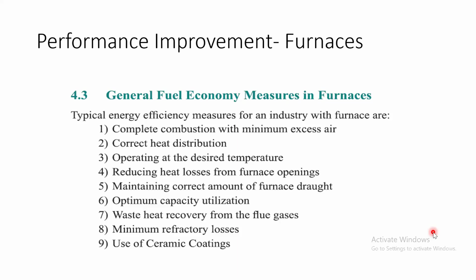And last is use of ceramic coating. Mind well, for insulation purposes and all other purposes, particularly to reduce the losses due to radiation and all. In major cases where the temperature exposed is more than 300 or 400 degrees centigrade, ceramic coating is very important, and it is also important for protection against high temperatures of 500, 1000, 1200 degrees centigrade. So in order to get good effectiveness of insulation for high temperature furnaces, it is always preferred to go for ceramic coatings. So use of ceramic coating is very important for performance improvement.